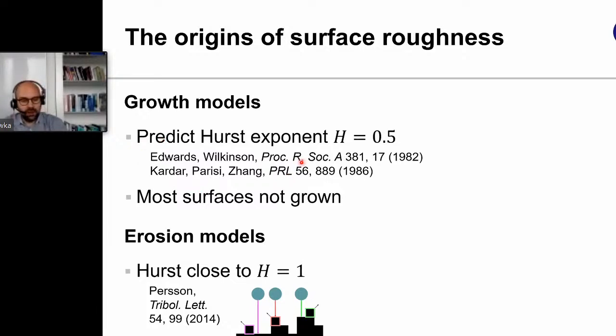But of course, the surfaces that we look at are mostly not grown. There's erosion models that also predict self-affine scaling. This is one example of Persson's work that predicts a Hurst exponent close to 1. But I would like to argue that most of the interfaces that we look at are actually interfaces that have experienced deformation. So they have been machined, they have been polished, and then we use them in a tribological context, so they have been worn down. So they experience plastic deformation and fracture.